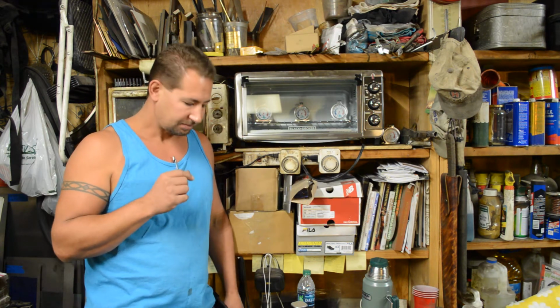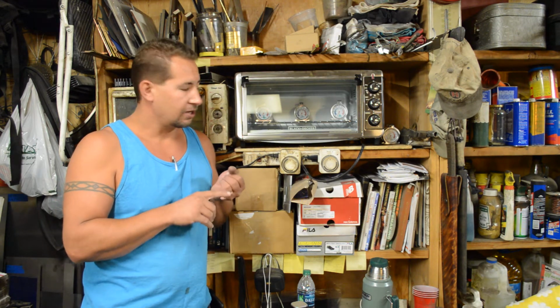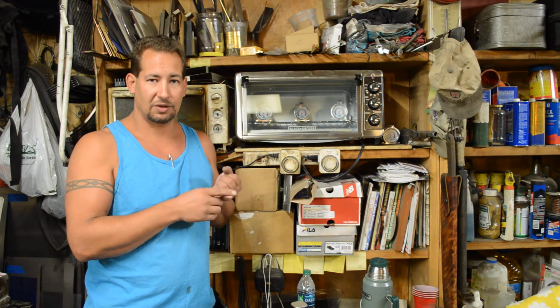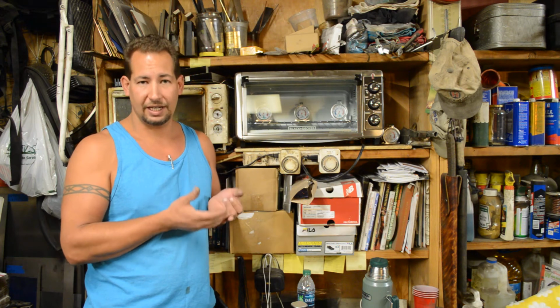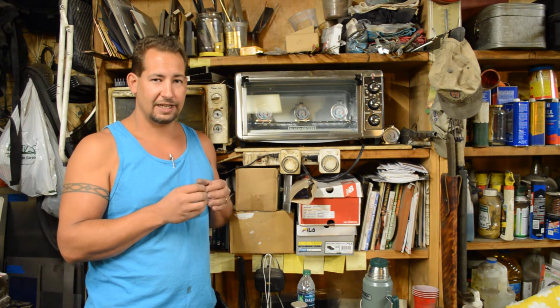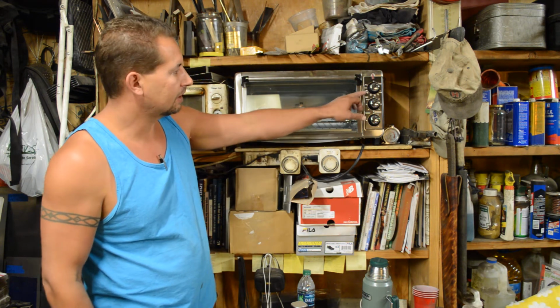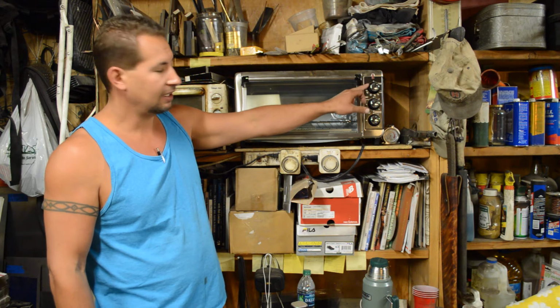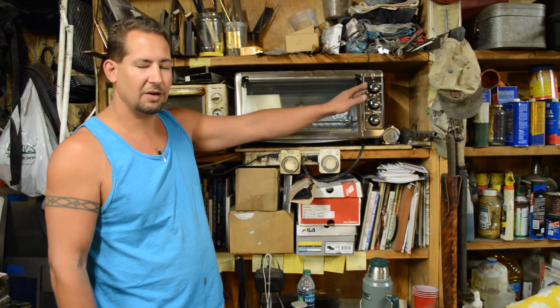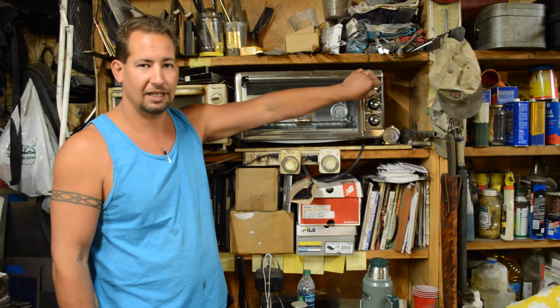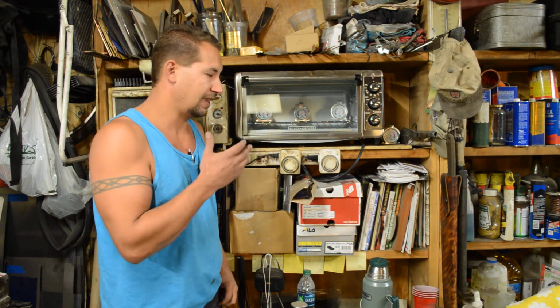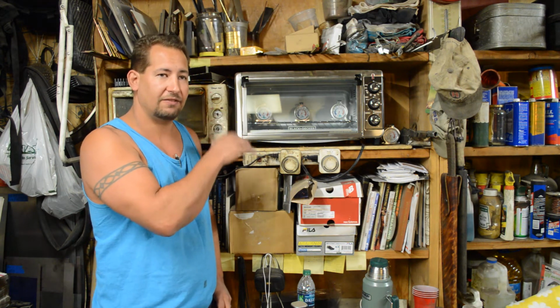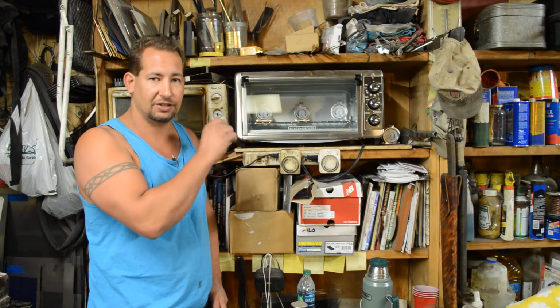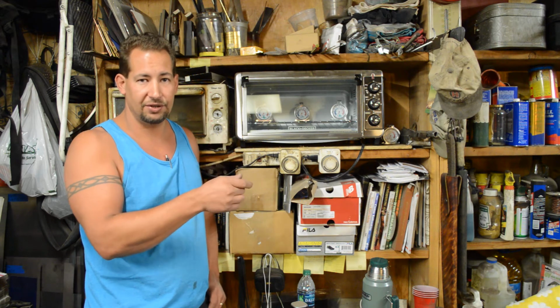The problem with toasters, you've got several of them. Okay, so your toaster oven, generally speaking, doesn't have the amount or the quality of insulation that a heat treat oven or a kitchen oven would have. The controls aren't as precise, both in the repeatability of the controls. So let's say you turn this right here, the temperature setting on this toaster. If you turn it off and then you turn it to 300, and then you turn it off and then you turn it to 300 again, sometimes they won't return back to that same setting. There's slack in the knob. That's a big problem. Also, if you set it on 300, is the oven actually coming to 300 degrees? Or is it going to 350, or is it going to 250?